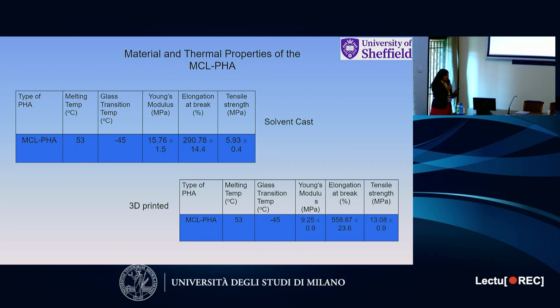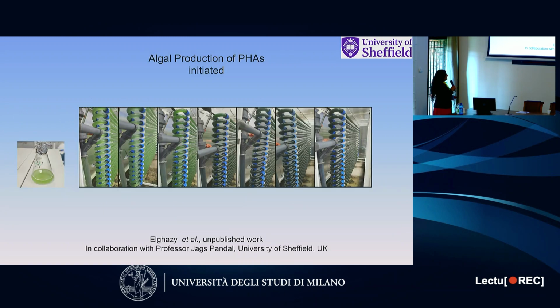Again, looking at the properties, you can see here the elongation at break is much higher than the previous polymer, about 290% and 558%, depending on how you've processed them, but the Young's modulus value is much lower. So we have 2 types of polymers, one rigid and strong, the other very elastomeric and not that strong. I also use energy and sunshine, as you have in Italy. We don't have much of that in the UK, but I'm trying to use whatever we have for the polymer production. So algal production of PHAs is another thing that I've started with Jags Pandal at Sheffield.